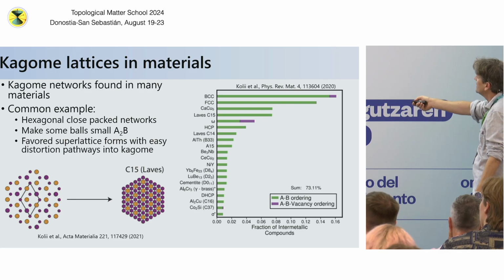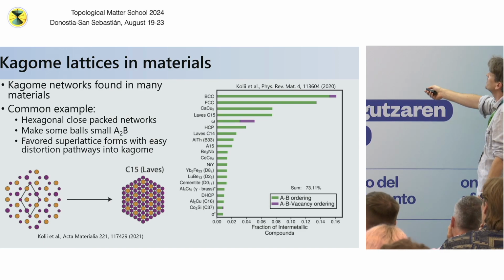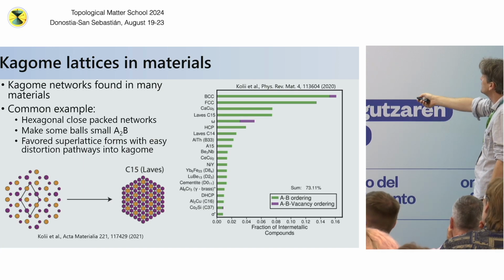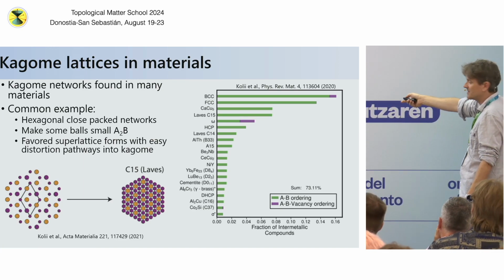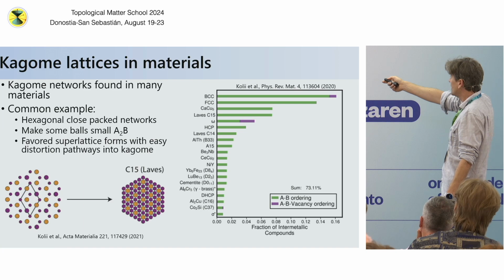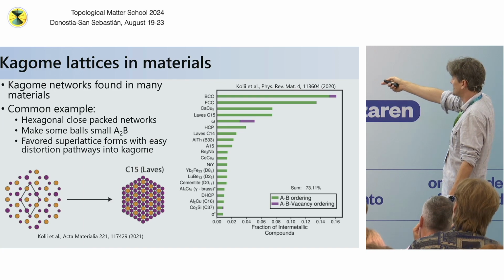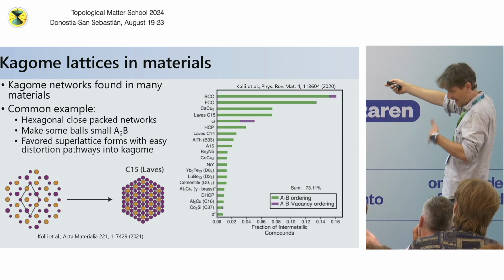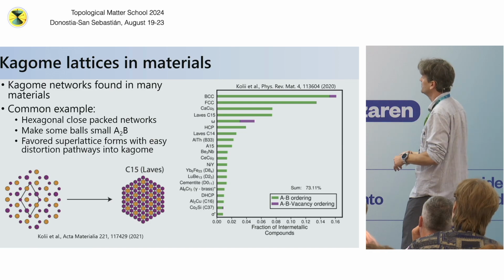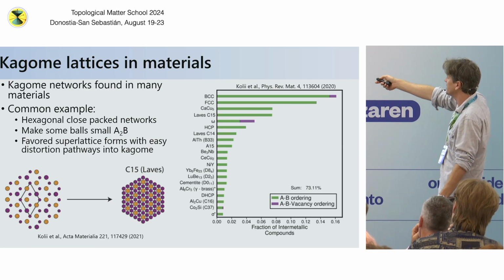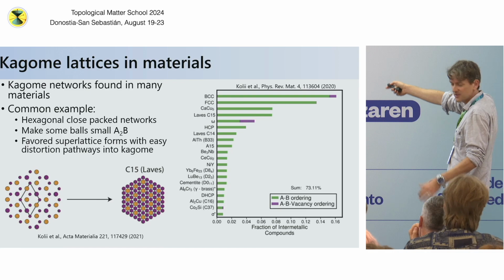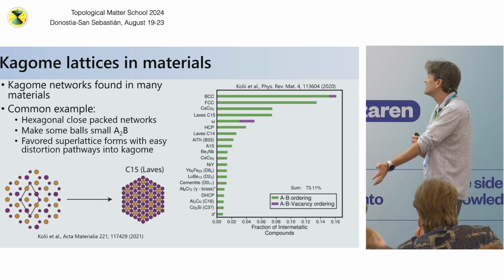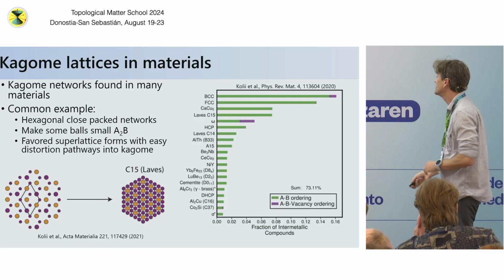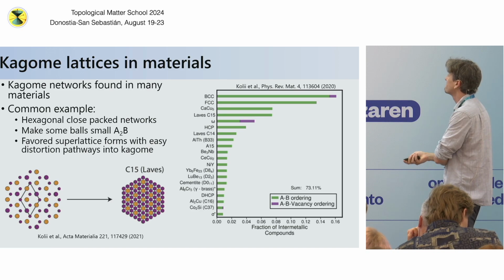And in fact, if you look at the histogram of the number of known binary intermetallics, where you have some type of A-B site ordering, a lot of the most commonly formed variants, such as the C15 Laves phase, have host networks of Kagome connectivity. This is a three-dimensional material, but it just goes to show you that the Kagome networks themselves are reasonably commonly formed in nature. Okay.